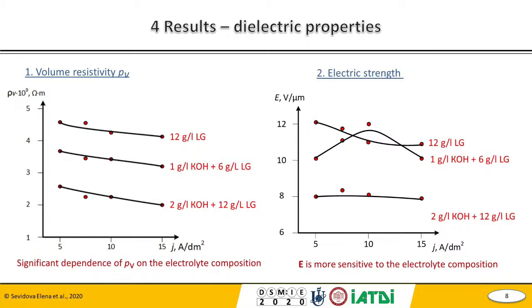We can also notice a significant dependence of volume resistivity on electrolyte composition, and the same situation holds for our electric strength measurements. Actually, it is in analogy to our previous research. We can see the results for the 2 g/L KOH + 12 g/L LG electrolyte, and as a result, we can also see that electric strength is more sensitive to our electrolyte composition. And our results, and in conclusions,